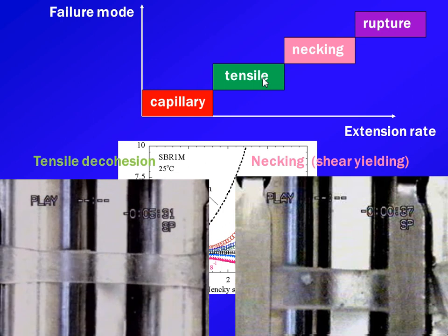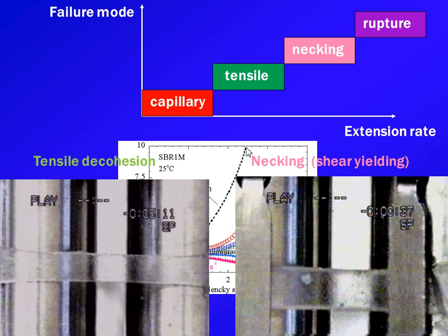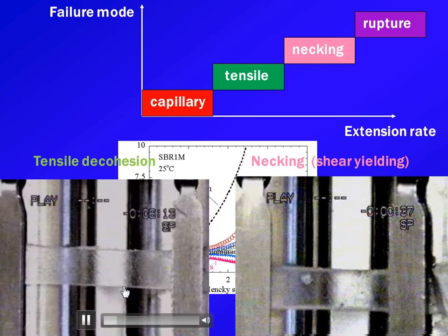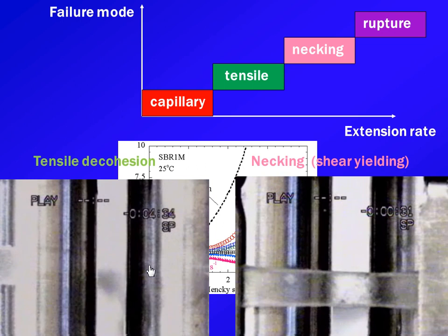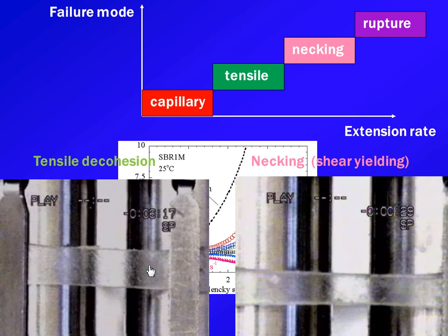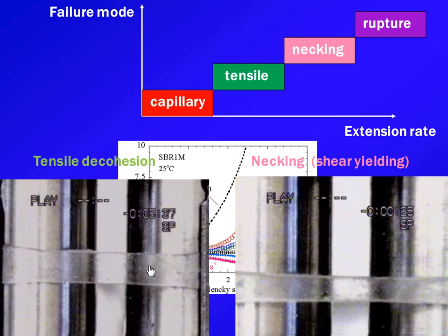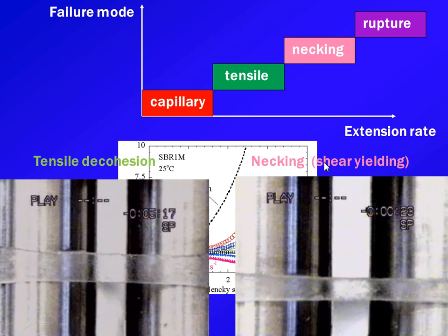tensile failure. You watch, it happens at low rate. This movie is sped up. You can see that it's being sped up. Look at that. It breaks very sharply, quote-unquote rupture-like. And then when you go to a higher rate, it stops behaving like this. The contrast between them is quite drastic. It doesn't do that vertical rupture-like behavior, and instead you may call it necking.